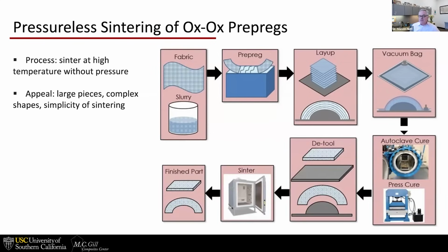You can see it goes through a lot of the same process steps that a polymer composite goes through, because you're making prepreg essentially, and laying up the prepreg, vacuum bagging it. Even, okay, we use the term cure. It's not really cure, but what comes out of the autoclave is a green state ceramic that can hold shape. And then it's subsequently sintered in a really big furnace.